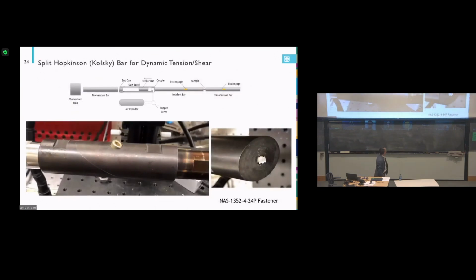So that's compression shear. What about tension shear? So there's one example when we test a fastener. With the fastener, usually you put something, you bond them together, right? But if we pull it this way, that's uniaxial. Then what if we put an off-axis like this? The fastener is subject to tension shear. So that's why we put an interface here. We bolt these two pieces together, but we pull out with some kind of angle. We can design the angle like 30 degree, 45 degree, 60 degree, and even 90 degree. 90 degree is nearly close to pure shear. So then we see what happened over there. So let's think about something for specific applications to better simulate the environment.